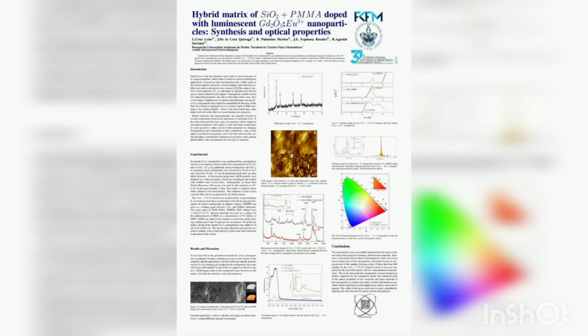In the experimentation, we synthesized the nanoparticles by a precipitation reaction in an aqueous solution with a europium concentration with gadolinium nitrate, and we used distilled water as a solvent. We also use ammonium hydroxide as an agent to start the reaction in this aqueous medium.